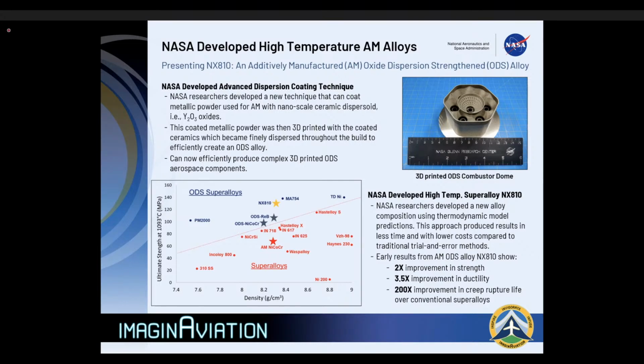And what we ended up doing instead was coating the nickel, cobalt, chrome powder with nanoscale yttria. Yttria is yttrium oxide, and it's usually the type of oxide that is used for ODS alloys. It's very stable and very inert, and it seems to actually help your oxidation properties when you incorporate it into your metal. And through a process called acoustic mixing, a high energy mixing process, we found a way to coat the nickel, cobalt, chrome powder that we purchased for additive manufacturing with the yttria, and then take that coated powder and put it into our AM machine. What was really nice is even after coating it, we didn't change the morphology of the powder, and the flowability of the powder was just as good, if not a little bit better. And so we were able to put it in the machine easily and start printing with it.